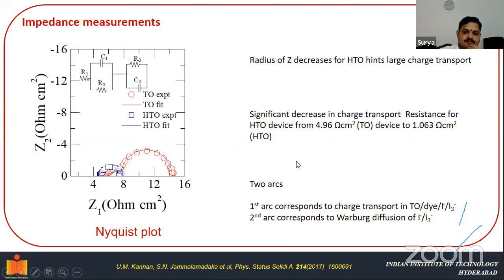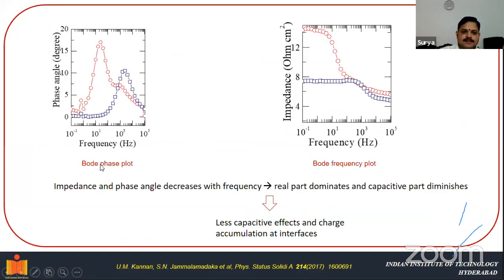From the impedance analysis, we can say that the resistance, or the impedance, of the device decreased as soon as we added holmium to titanium dioxide based solar cells. These arcs we fitted with this circuit and extracted the resistance of the device. We also plotted the Bode phase plot and the Bode frequency plot.